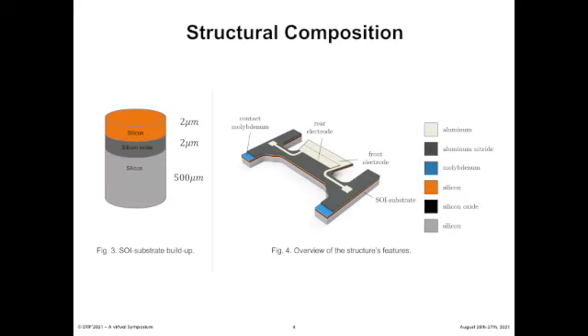For the device, we use a silicon on insulator or SOI substrate. And this substrate consists of two silicon layers and has a silicon oxide layer in between. And onto this substrate, we apply two material layers, molybdenum and aluminum nitride. So we have two electrodes, which are above and below the aluminum nitride layer. And this enables us to use the piezoelectric effect to create this excitation of the device.